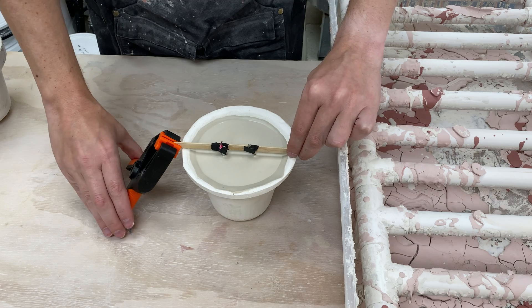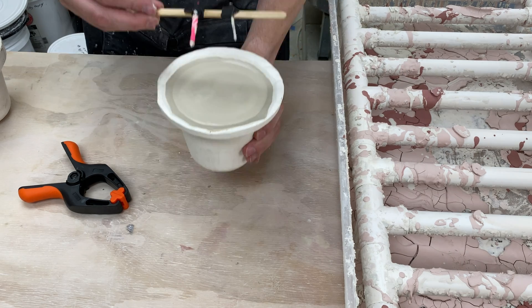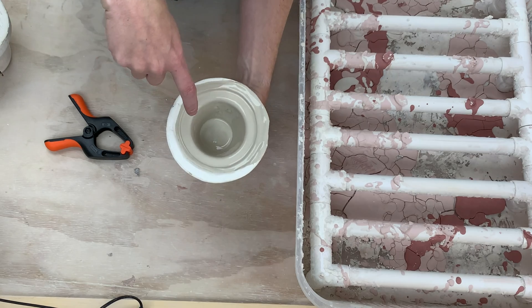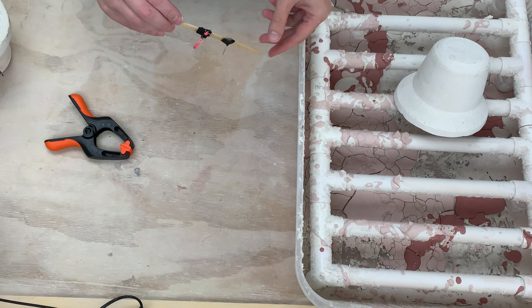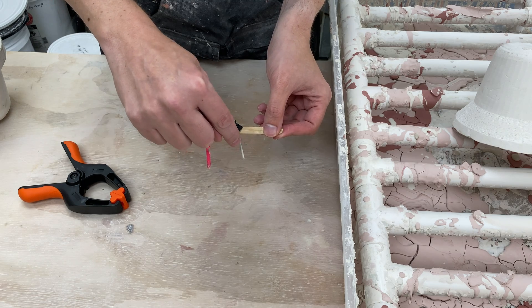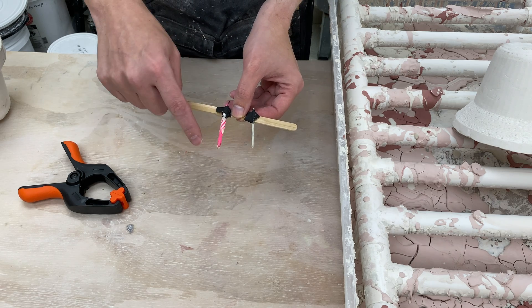All right, the walls have formed. Let's take out our test here. Yeah, we can see slip on here. Let me dump out the slip. We can definitely see some hints of where the holes are, but they're covered up. Let me go ahead and drain this out the rest of the way. I have my slip drainage table here, so I put it at an angle away from the holes. So this is interesting — in me just holding this now, it has come off the wax, but it is still attached to the nail. That is a surprise. So I was wrong about this part. There is something to using the wax for the pins instead of the nails. That's interesting. This is why we test things. I'm going to let my pot drain for about another half an hour so the excess slip will drain out and the pot will firm up, and then we'll try and demold it and see what we're left with in terms of the holes.